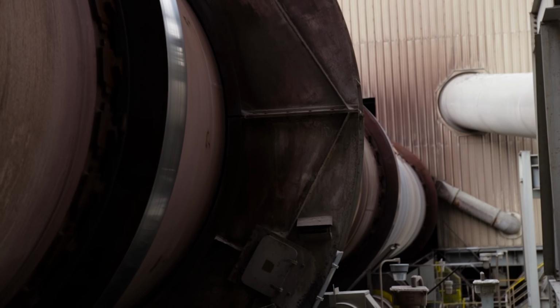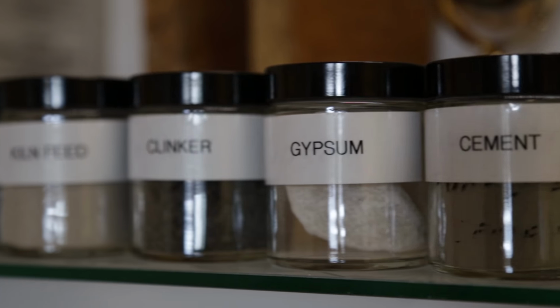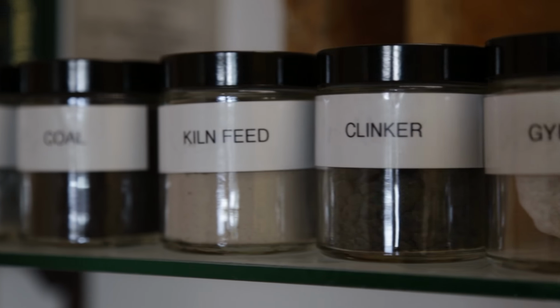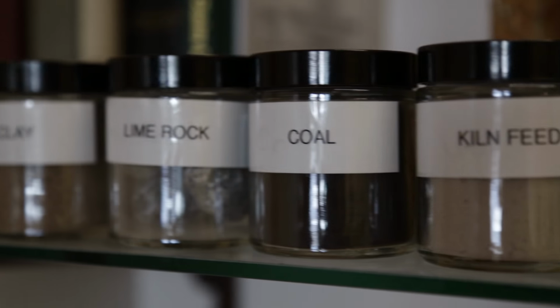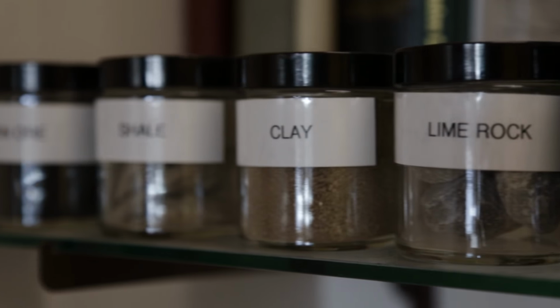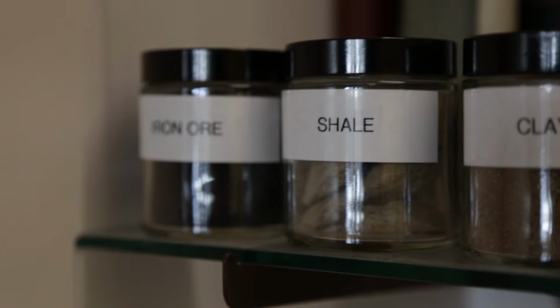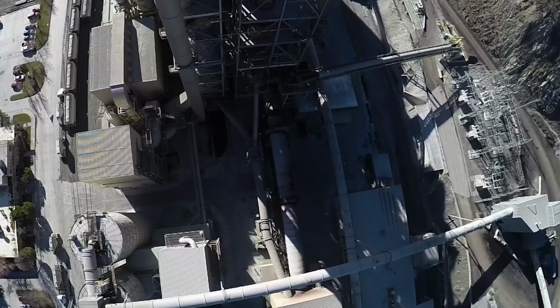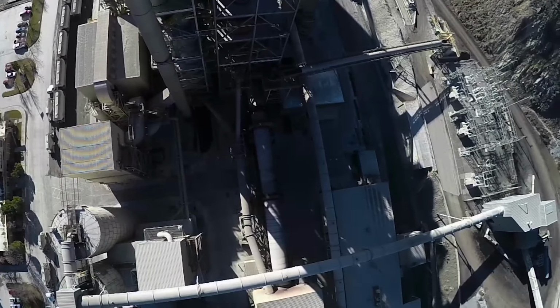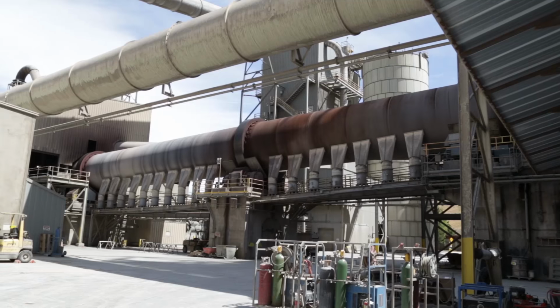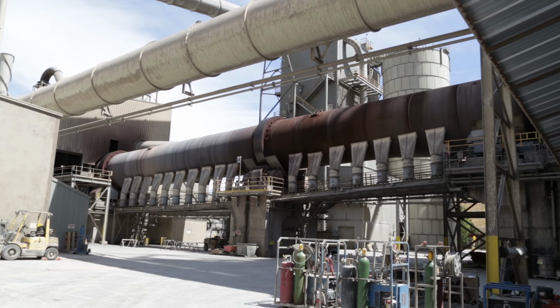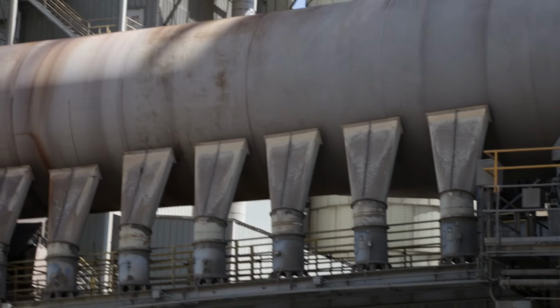The kiln is 216 feet long, 14 feet in diameter, and it spins about 3 to 4 rotations per minute. Our kiln can make 3,300 tons per day of clinker. Clinker is the intermediate product before we make cement. The kiln is made out of 1-inch thick rolled steel, although in places it can be up to 3 inches thick underneath the tires, which are the main supports for the kiln. And on the inside of that steel, it's lined with a 9-inch thick refractory brick.